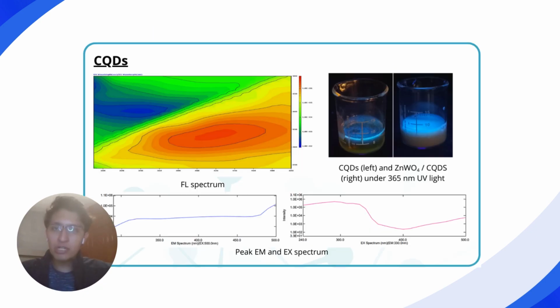Now, talking about our results, let's start with the carbon quantum dots fluorescence spectroscopy. This was done in order to determine the presence of carbon quantum dots and not just any kind of organic matter. We can see the peak intensity at the 430 nanometers emission wavelength and 350 nanometers excitation wavelength. This is consistent with results found in literature. Now, we can physically see this behavior in the photos presented under UV light for both the carbon quantum dots and the composite, emitting a blue light.